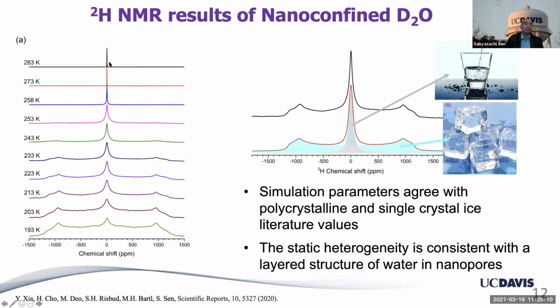And that's what makes the NMR signal very narrow. But as you cool it down, you can see this emergence of this very broad signal. And I'm not going to go into the details of why the shape of the signal is like this. So you have to take my word for it that this is extremely well understood and can be theoretically calculated. And this is the calculated line shape in teal. And this corresponds very well to the line shapes observed for single crystal ice as well as polycrystalline ice.